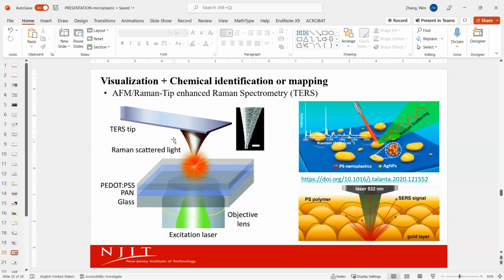So on the AFM, you have the tip over there, right? A very small AFM conductive tip, and you can place the Raman usually from the bottom. This is a commercial AFM-Raman. They are very powerful. I had a study a few years ago. We used these techniques to detect graphene, not plastic particles. The graphene absorbs Raman pretty strongly, very sensitively. And then we use AFM to analyze the surface, mapping, so we look at the whole surface. And in the meantime, the Raman signals tell us where the graphene oxides or graphenes are located on the sample surface. So this synergy allows us not merely to visualize, but also to chemically identify the particles.